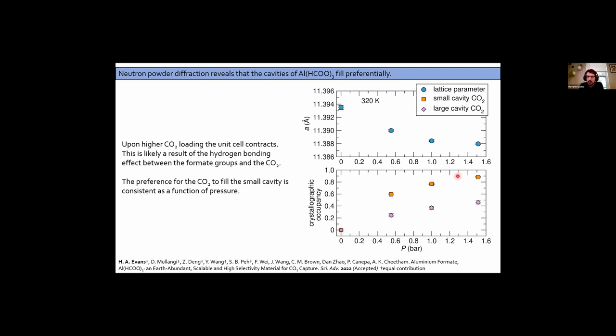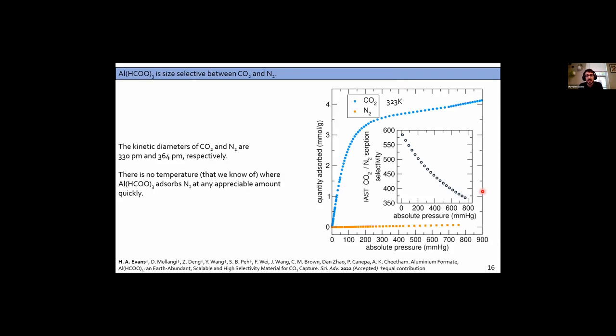And then as you track the crystallographic occupancies of the CO2 that adsorbed, you can now understand that the small cavity is being favored, whereas the large cavity is still filling, but to a lesser extent relative to the small cavity. And then I'll end with, you know, this material is not just good because it sucks up CO2, but because it's a molecular sieve. So this thing completely ignores nitrogen on any reasonable time scale and sucks up a considerable amount of CO2, right? So we're talking about a selectivity up in the hundreds at these elevated temperatures.